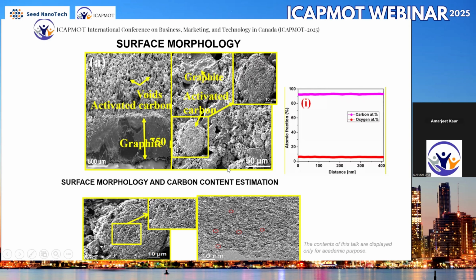The EDX study shows, from the atomic fraction, that we have 90 to 95% carbon, and a small amount of oxygen is also there in our activated carbon.